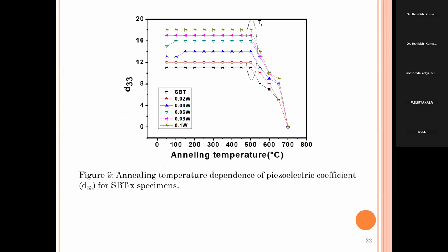So after conducting all the experiments, we found the piezoelectric constant of the material. Generally people take the piezoelectric constant only at room temperature, but for high temperature piezoelectric application, we have found the piezoelectric constant from room temperature up to 700 degrees centigrade.